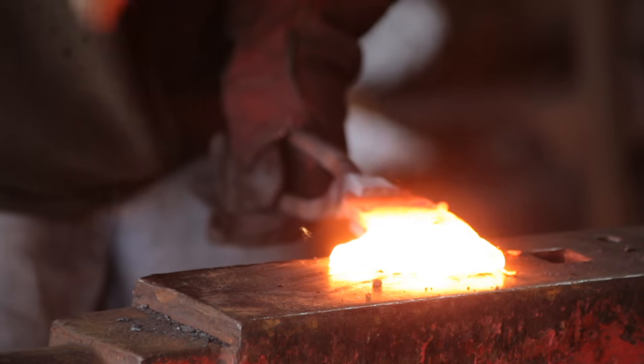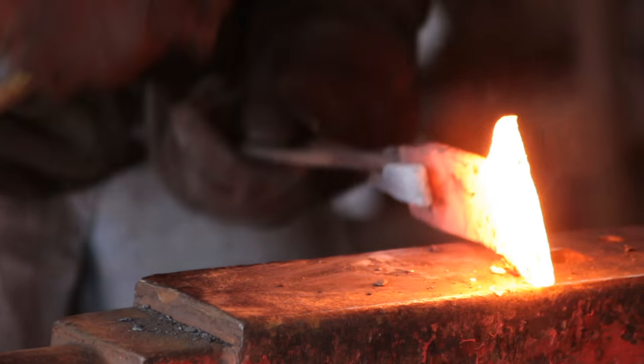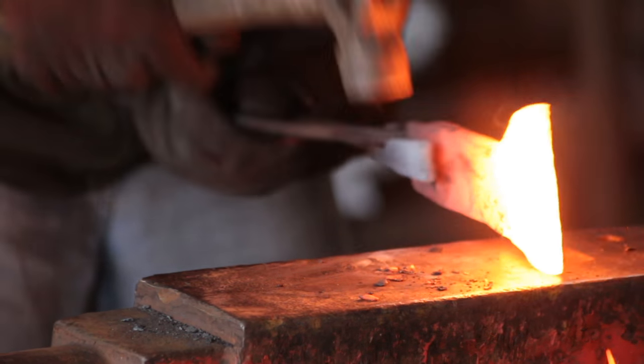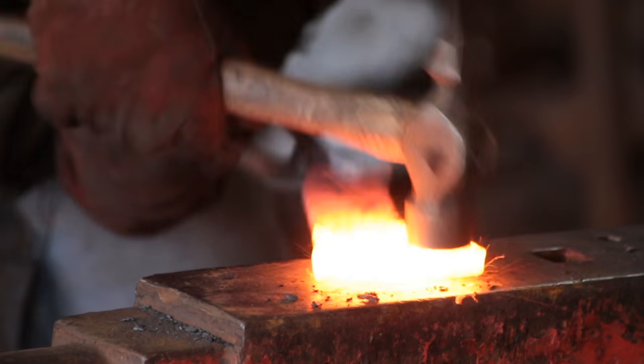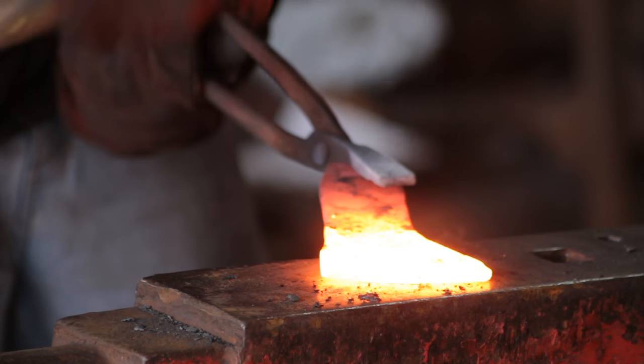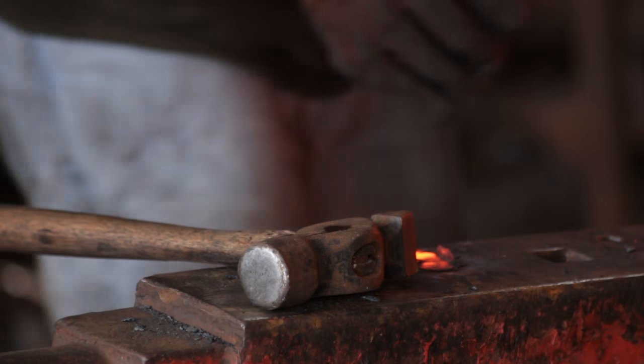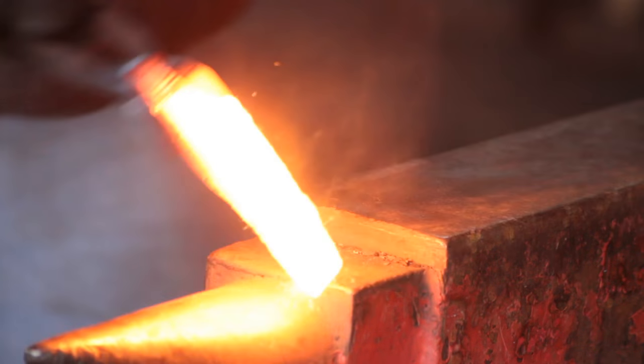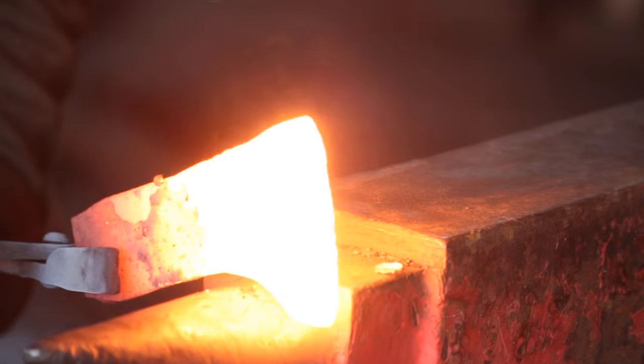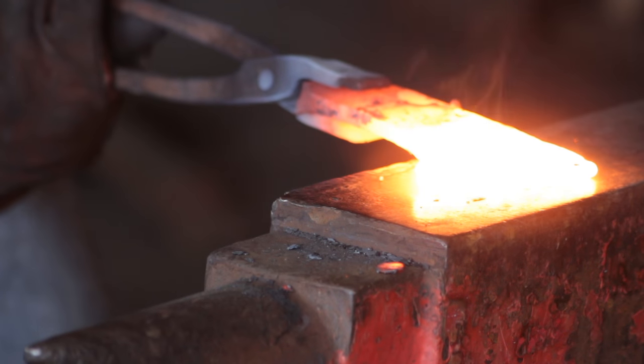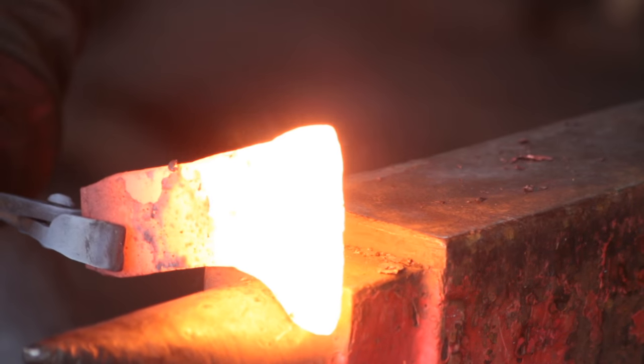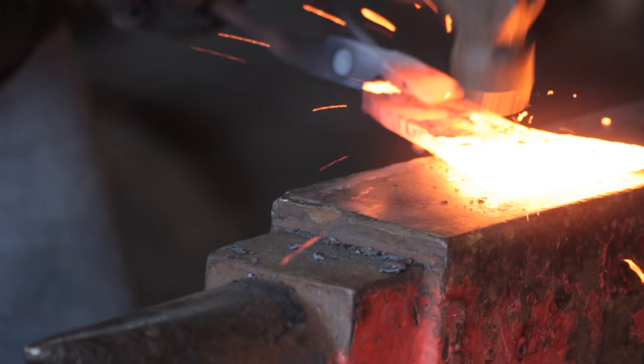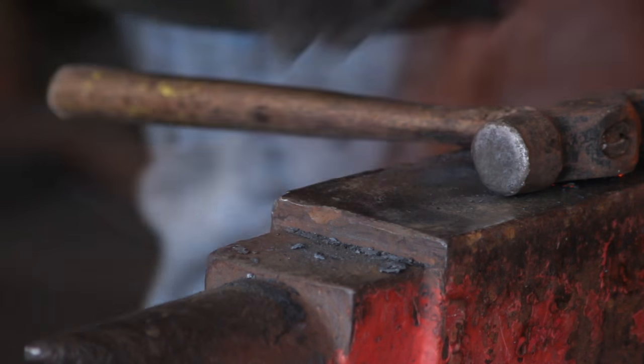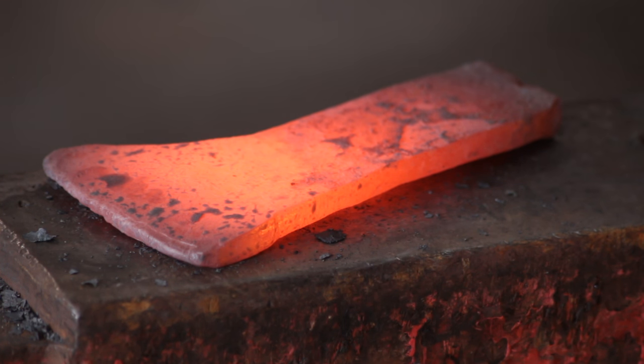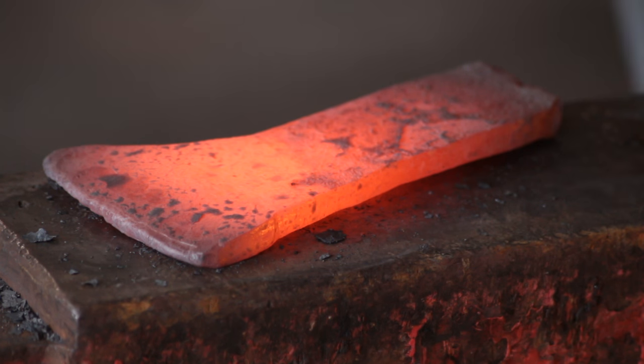After I've welded in the width of the blade, I'll just weld in the edges, close up any open seams, make sure there's going to be no galls in there, no cold shuts. Use the bit if necessary. So you can see by the curve on there how much it's spread by just welding in the carbon steel bit. But as you can see, the weld's gone in quite nicely.